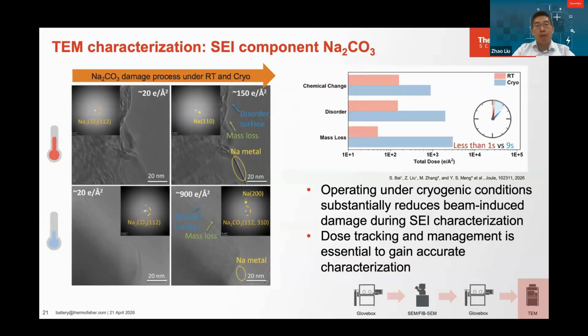Your sodium carbonate will turn to different materials, and there's a lot of damage mechanism also happening in the meantime. The cryogenic temperature, however, can give you a little bit more room for the dose to be able to endure on the samples. However, if you still reach out to more doses on the samples, you will still damage the sample. That indicates the cryogenic condition can actually reduce the beam-induced damage. However, dose tracking will still be very critical, because it's not like if you have a cryogenic temperature, you are already worry-free in these cases.